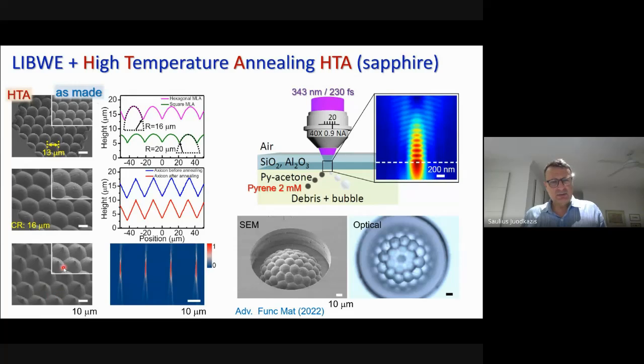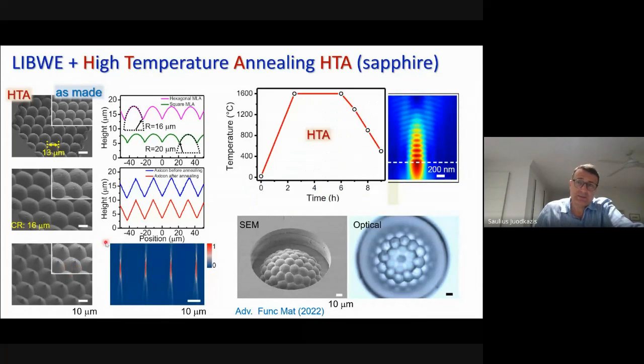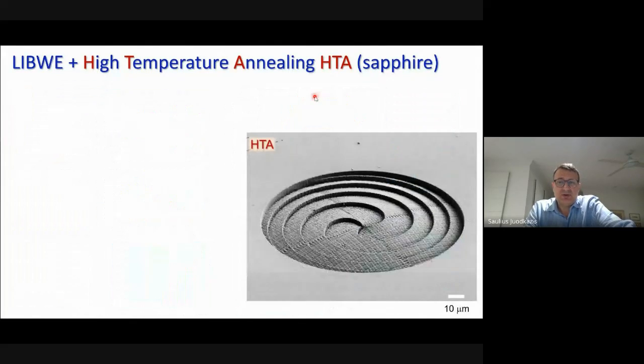So it's shown here, and sometimes we want to fabricate conical lenses, which are optical axicons with sharp noses. And how to do that? If roughness is not good and we want to anneal and make it smooth, with glasses, surface tension usually makes every lens spherical, which is not ideal. But in crystals and sapphire, even with high temperature annealing, and you see the temperatures here were running up to 1600, it's still 500 centigrade less than the melting point of sapphire. So sapphire is not changing, but the surface is modified and changing. So it's getting more flat, as you will see in the next image.